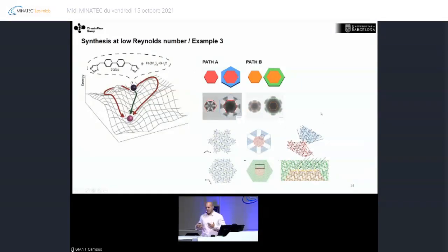Why do we think that the vertex is favored versus the face? If we look at the crystal structure, what we see is that the interactions here are ionic interactions, and these ones are via van der Waals interactions. So this is why we think that the vertex is favored, because the interaction is stronger than the van der Waals ones. But when we submitted this manuscript, one of the reviewers told us that what we were observing was just an artifact, and they didn't believe these results.